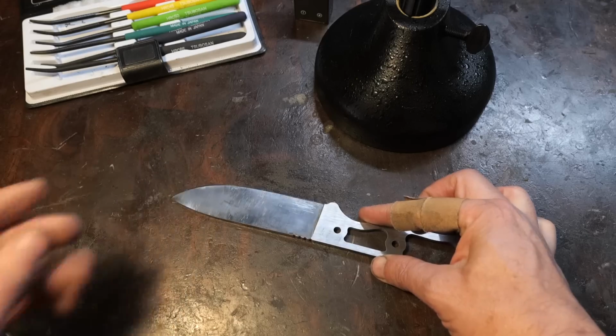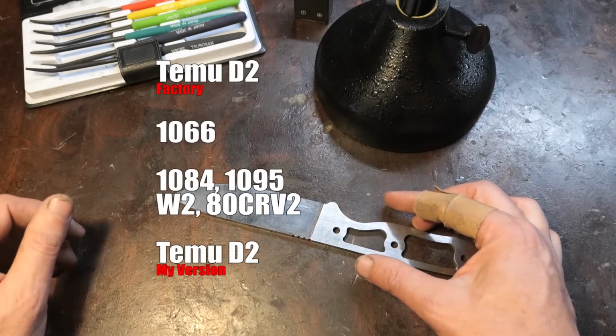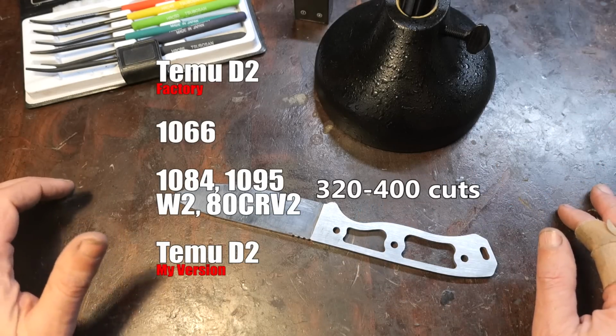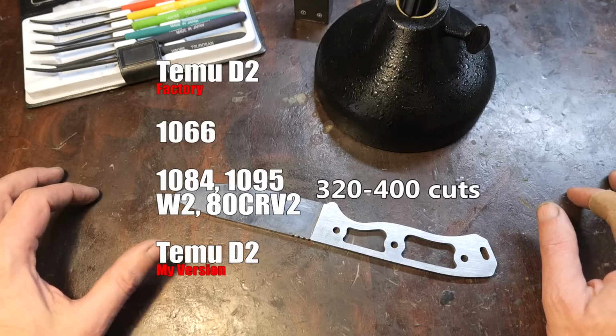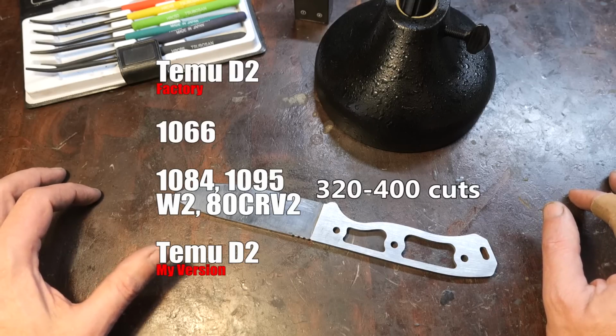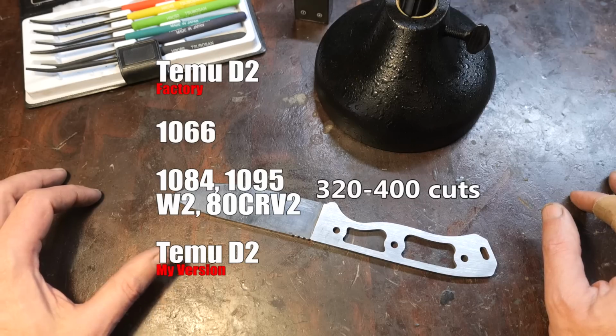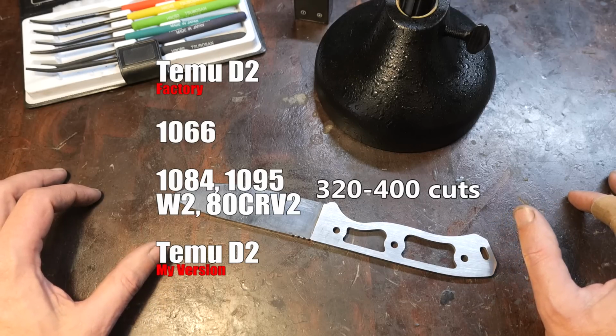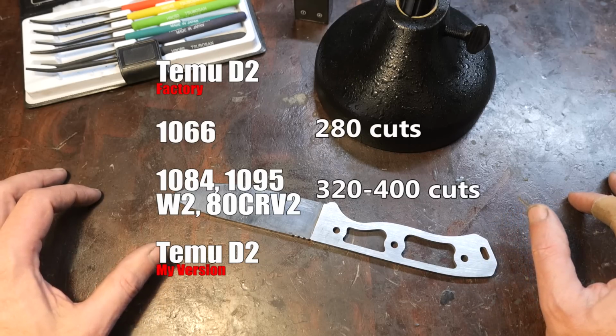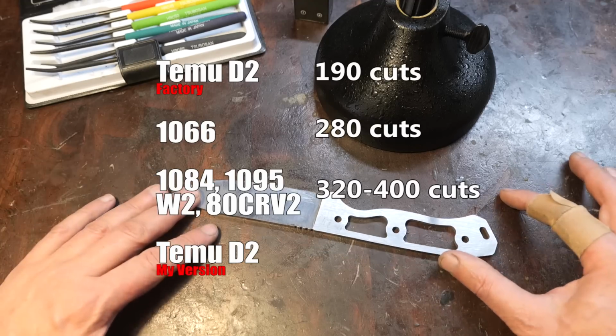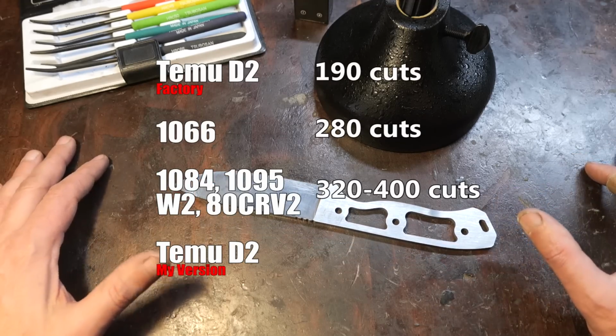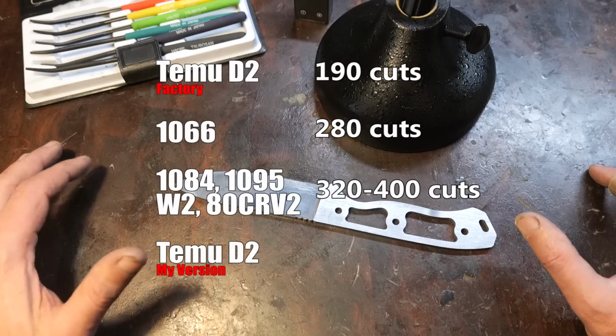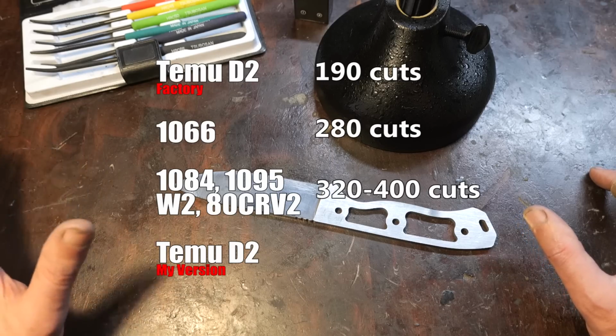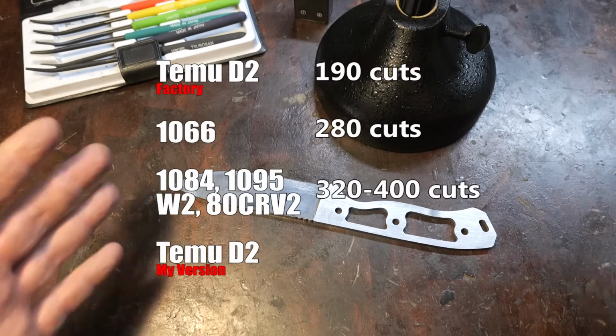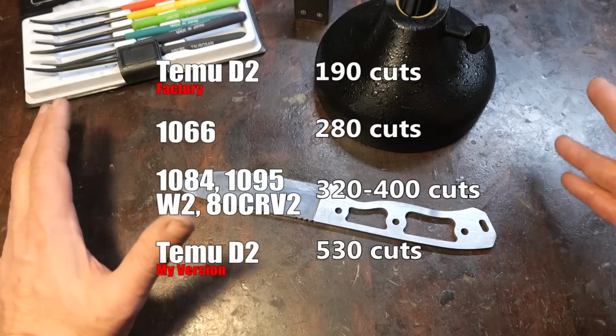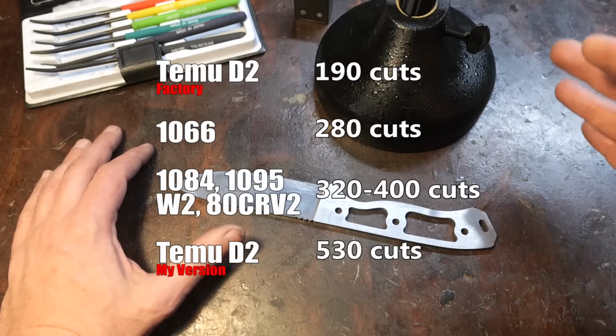For reference, on the rope test, I get about 320 to 400 cuts out of my knives made from simple forging steels like W2, 1084, 1095, 80CrV. I just tested a production knife made of 1066 that did 280 cuts. So this knife's original result of 190 was marginal at best, but not unacceptable for this price range, and actually is better than I personally expected. The fact that it just did over 500 cuts after better hardening and better slicing geometry is shocking to me.